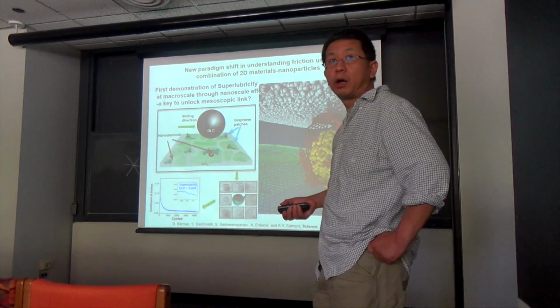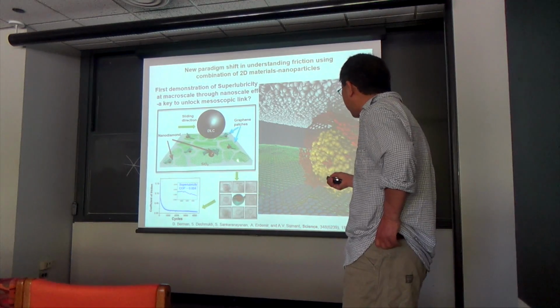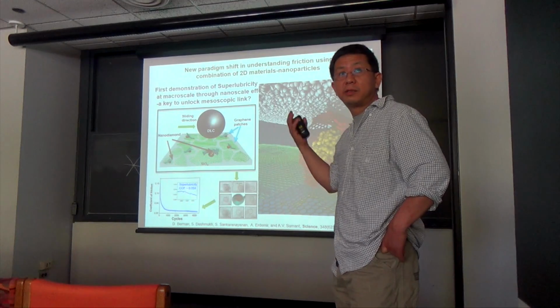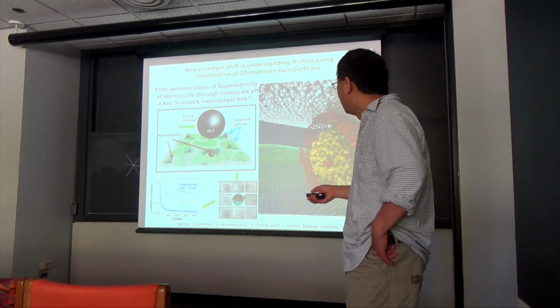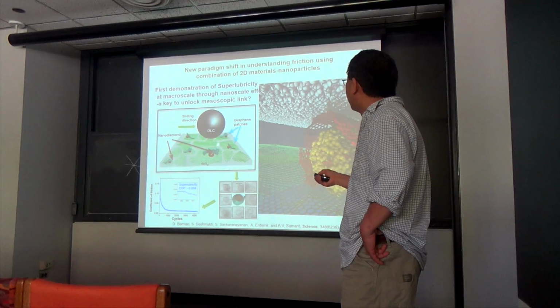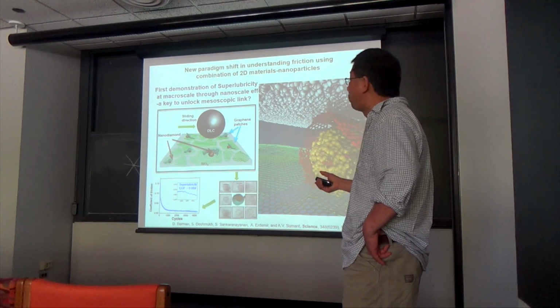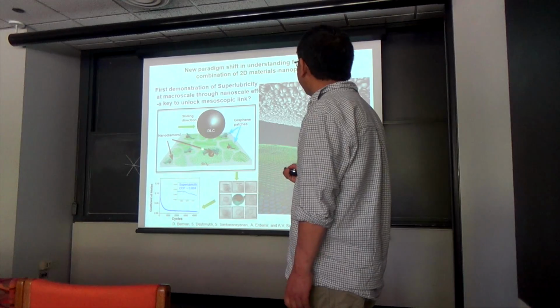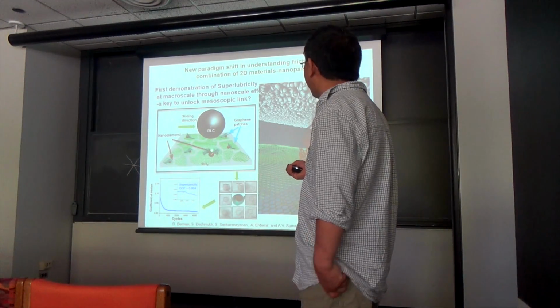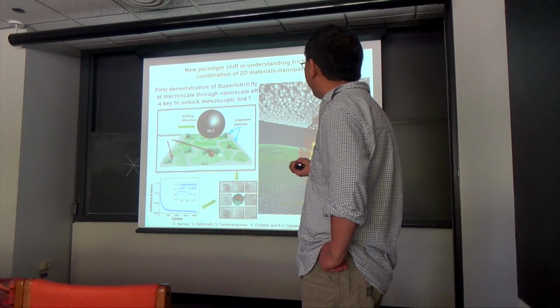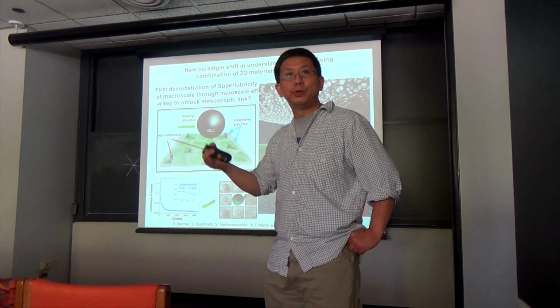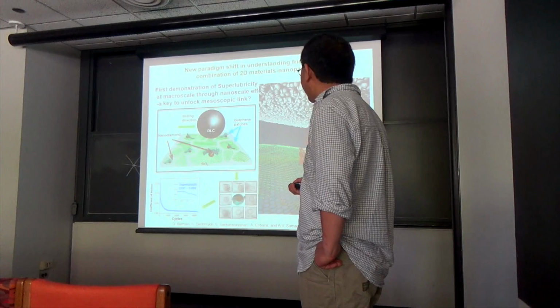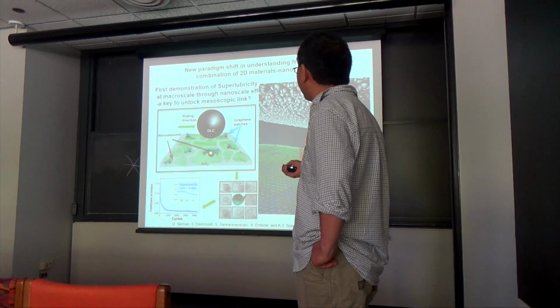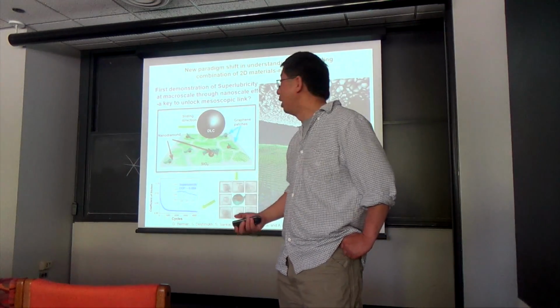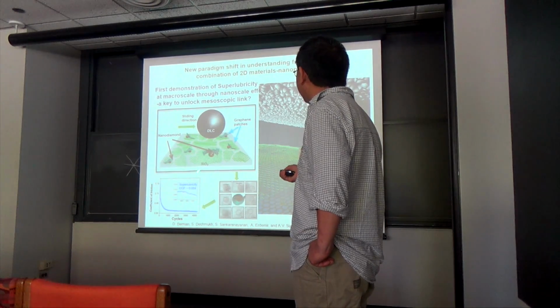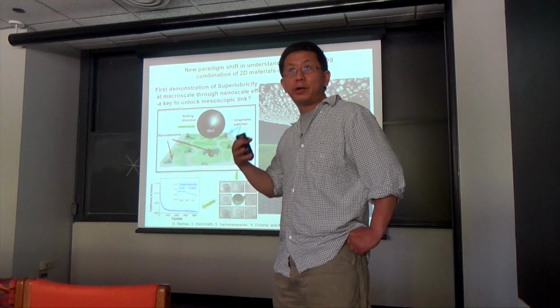Another example developed at Argonne is the so-called superlubricity behavior. These are experiments and theory, both done at Argonne, in our center. On the experimental side, people have been trying to spray some graphene onto a surface, looking at the friction, essentially. What they find is that if you put graphene sheets on the surface and then sprinkle a few nanodiamond particles onto it, the friction coefficient drops dramatically into so-called superlubricity conditions.